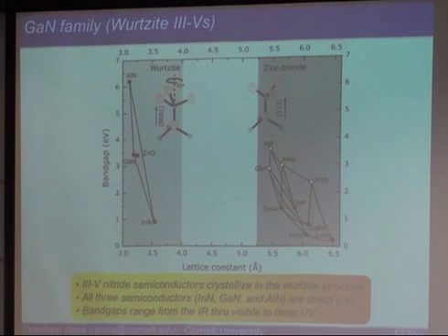It has a lattice constant that is slightly larger in this direction, the c axis, about 5 angstrom. In this direction and that direction, x, y, it is about 3 angstrom. So it's a hexagonal crystal, longer in one direction. You can think of the stacking as kind of twice in one direction than the other. Okay, that's the way to look at it at this point.